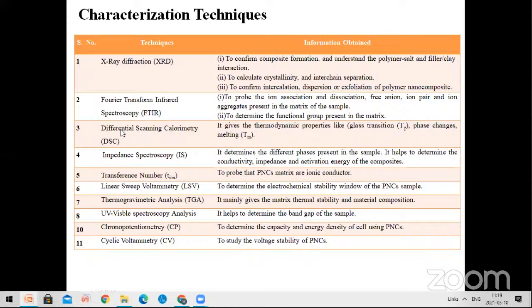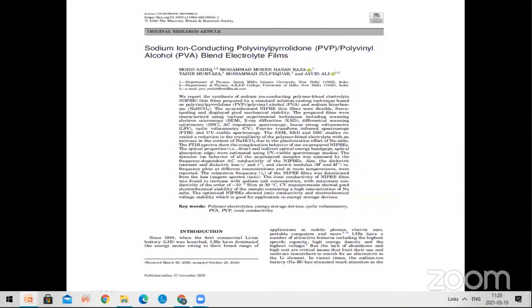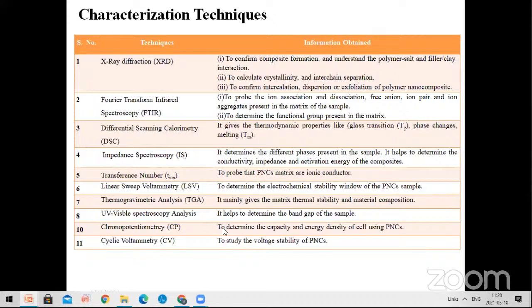And then we use differential scanning calorimetry for the thermal study. Impedance study is to find the ionic conductivity of these blend polymer electrolytes, and we also check the ion transfer, and linear sweep voltammetry for the voltage stability of this polymer sample. Thermogravimetric analysis is to find out the thermal stability of the material, and we also check UV-visible spectroscopy. It helps to understand the band gap of the material. And we check the voltage stability of the polymer electrolyte with the cyclic voltammetry technique.